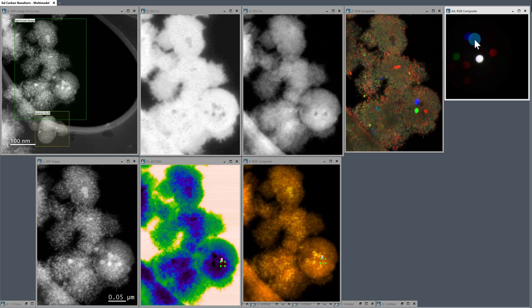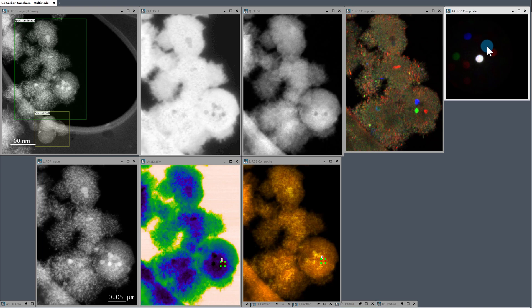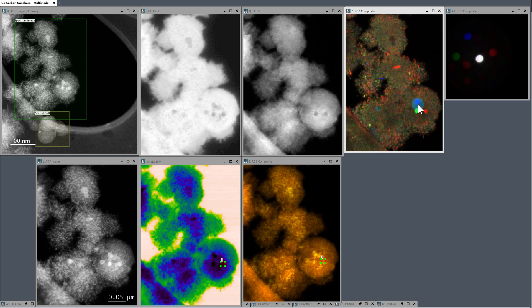But then you can see very clearly the blue diffraction disk, the green and the red, and they're all in different places. So this I'm really using as a key, or a reference to allow me to interpret the contrast in the composite that I just generated. And what's very clear is we have in the region I was targeting three particles that are in quite different orientation. So we have this blue region, the green, and the red.